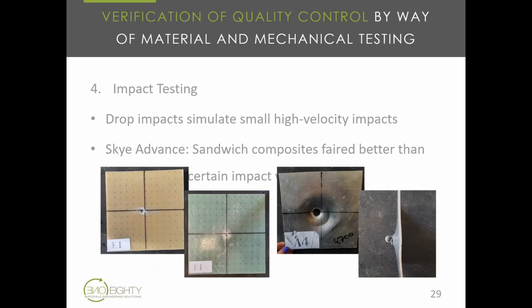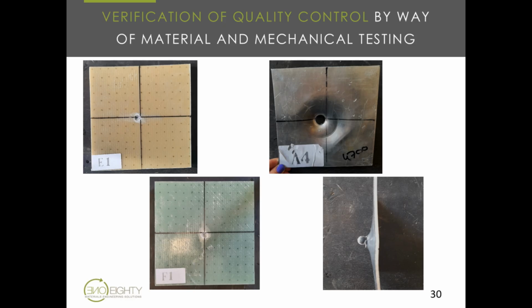And it actually, at some impact velocities, the sandwich composite fared better than the aluminium. The aluminium was punctured directly through, whereas the sandwich composite, that first composite layer, laminate, was affected, but because the PVC foam behind absorbed that energy, it didn't puncture all the way through to the back laminate, which means that you wouldn't have had water penetration into the vessel. You would have had it into the foam, but not into the vessel. Whereas with aluminium, you would have had water going straight in through there, which was a very interesting case study.